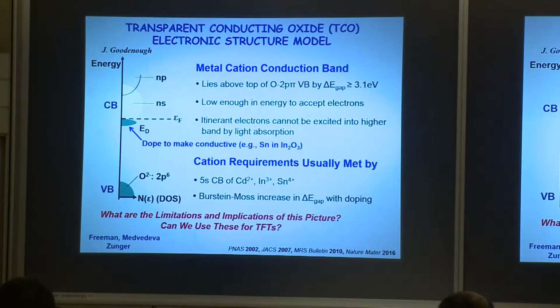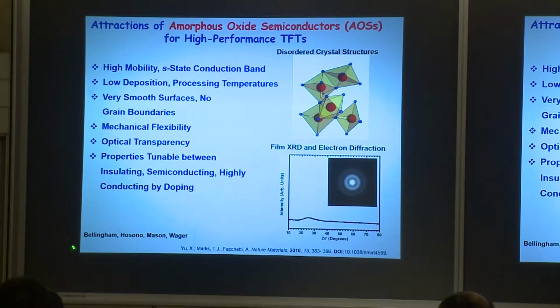So what are the implications of this picture? Can we use these for TFTs? And then I want to introduce one other historical twist. There was a researcher, Bellingham in the UK, who for some years published work where he claimed he had made amorphous oxide conductors. And everyone said, oh, that's sort of weird. That doesn't really make a lot of sense. But Hideo Hosono at Tokyo Tech saw that there was something really interesting and unusual. And in fact, here's some that we grew just to show you. So if you grow these at low temperature, you can get amorphous oxides.